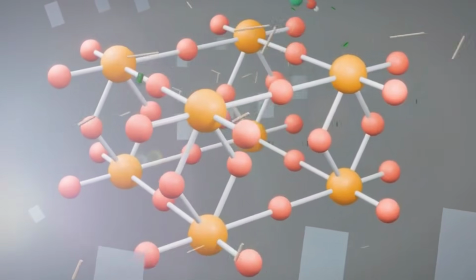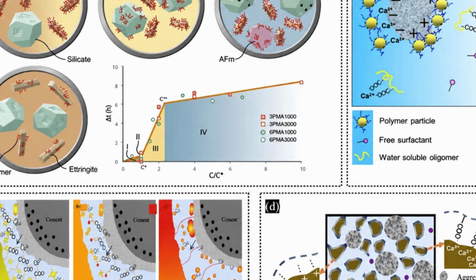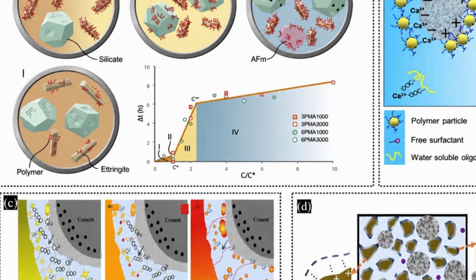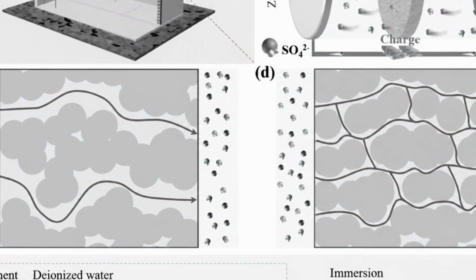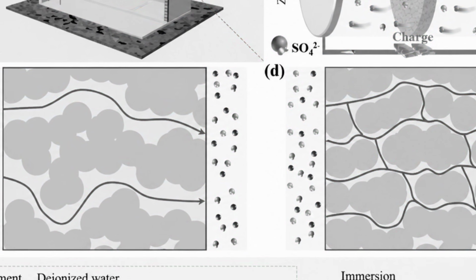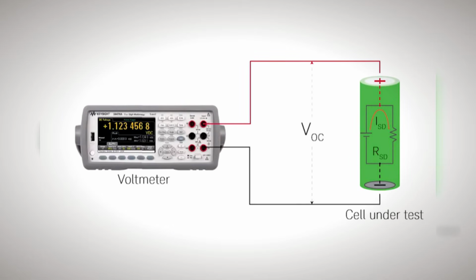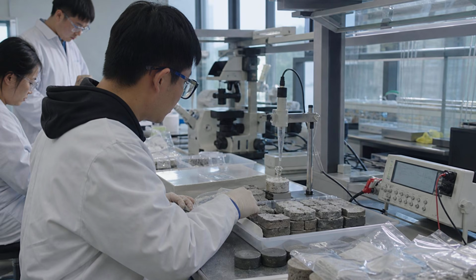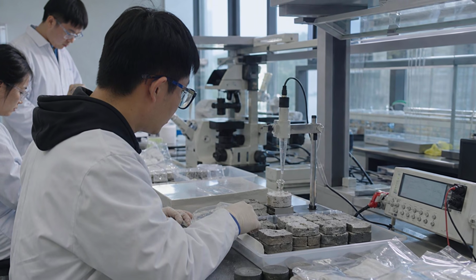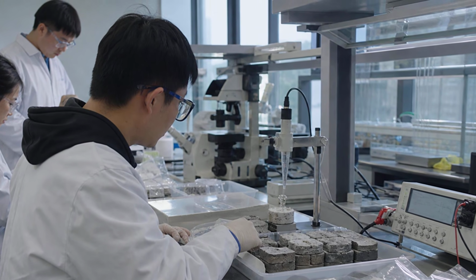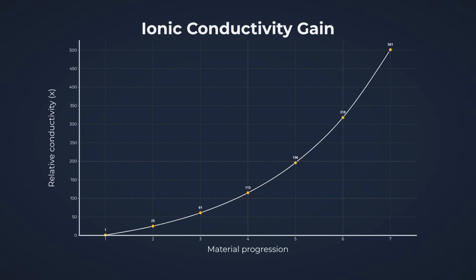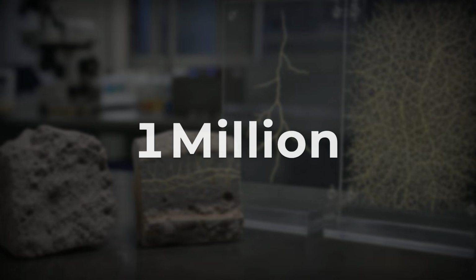That structure lets ions move through it fast while blocking electrons from taking a shortcut. Blocking that shortcut is the entire game in a supercapacitor, because a shortcut is a leak, and a leak is a battery that drains itself overnight. By tuning that microstructure, they push the ionic conductivity of the cement up by 6 orders of magnitude compared to ordinary cement. 6 orders of magnitude is 1,000,000 times.